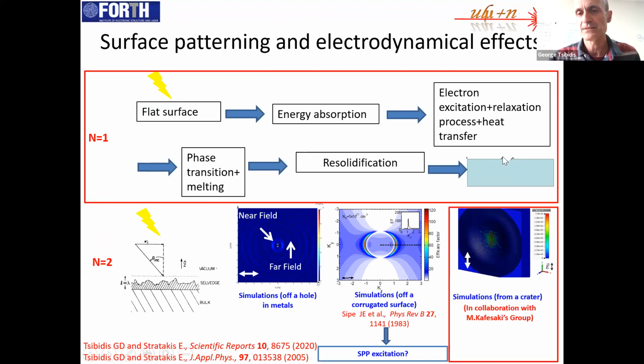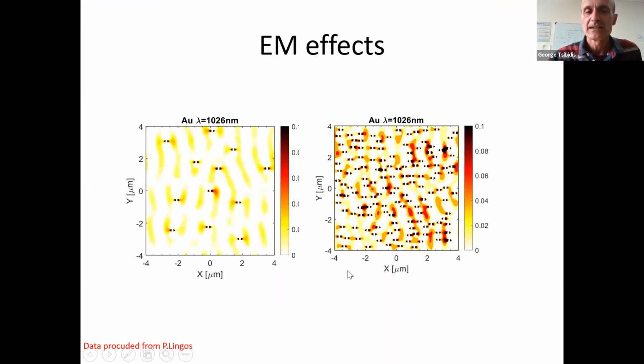So we start, the first thing is we produce with one pulse this corrugation, let's say. So if we irradiate a corrugated profile, and we solve the Maxwell equations to describe the propagation of the electromagnetic field, then we see that the far fields, the surface waves that are produced after scattering on these defects, interfere with each other. They produce this electromagnetic fingerprint, and they interfere also with the incident beam.